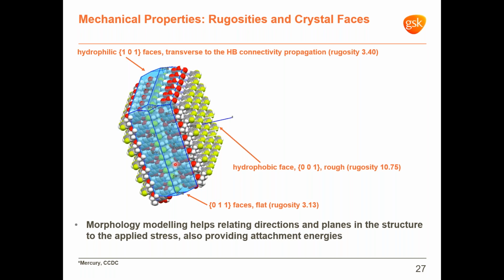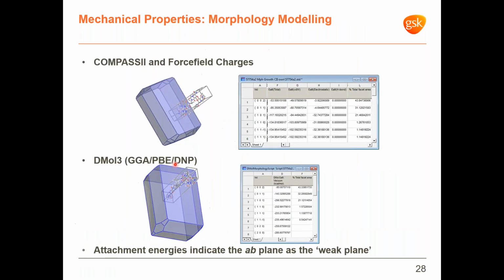Most importantly, energy-based morphology modeling provides a quantitative estimate of the attachment energies across different planes in the structure. And here is the overview of the growth morphology modeling for our API development form crystal structure at two different levels of theory. We usually start with a force field based model for an initial quick assessment, which we then validate with a more accurate DFT based model. In this case, the two models are in good agreement, both indicating the AB plane perpendicular to the 001 direction as the weak plane, followed by the plane perpendicular to the 011 direction, approximately parallel to the AC plane.